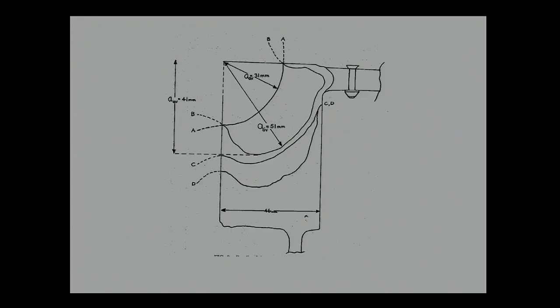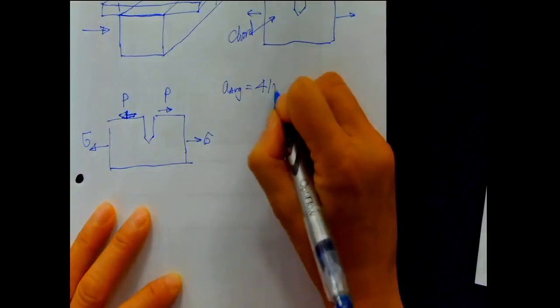Okay. So in this case, we have, back to here. So we want to calculate the arrest, for which is this line over here. And obviously they are not very well behaved as a quarter circle as what we expect. So we just take the average of those two and then use the crack length of 41 millimeter for our calculation. So we have A average is equal to 41 millimeter.